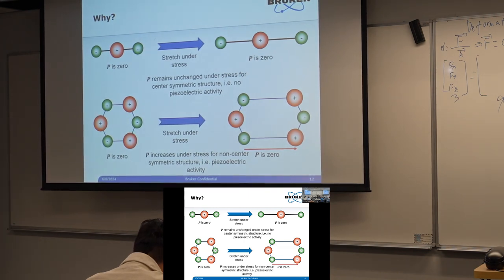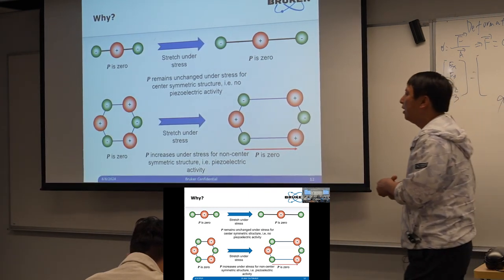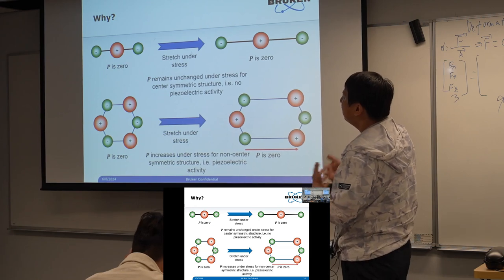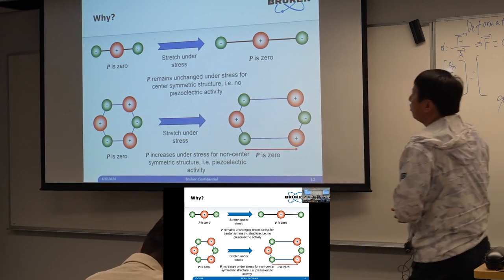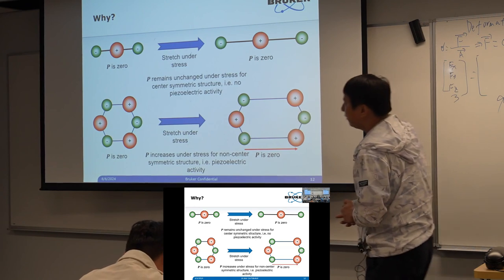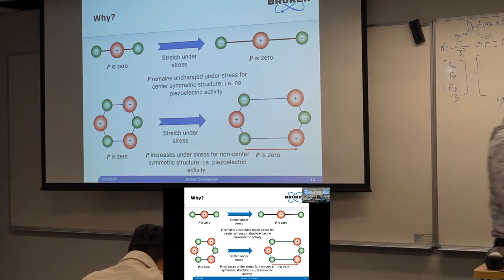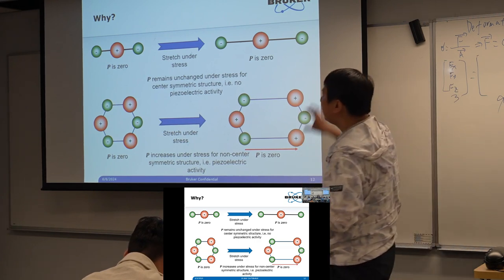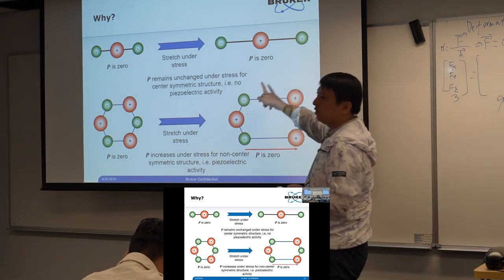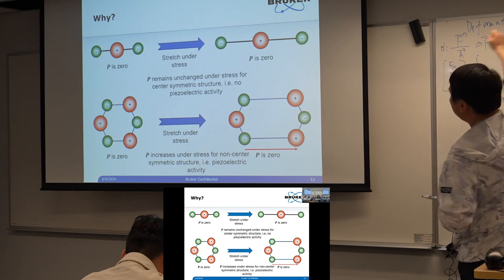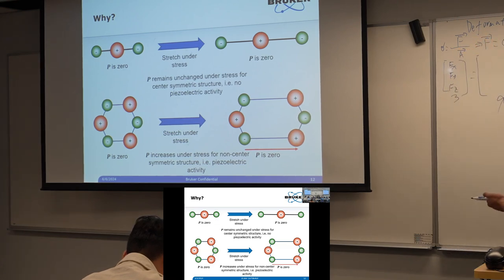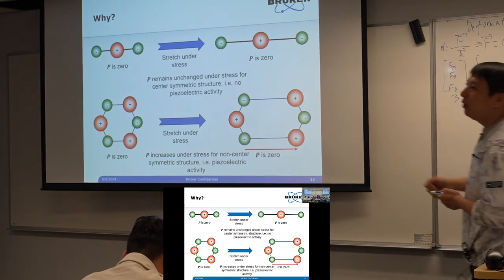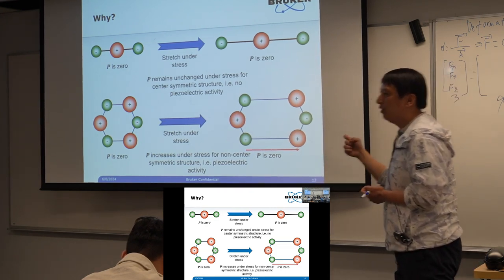If we get that, we can make it very easy to study piezoelectricity. Once you want to know whether your material is piezoelectric or not, the first thing we will do is not to test the piezoelectricity directly. We do not squeeze it to see if the polarization changes. No, we will just do the structure study first.